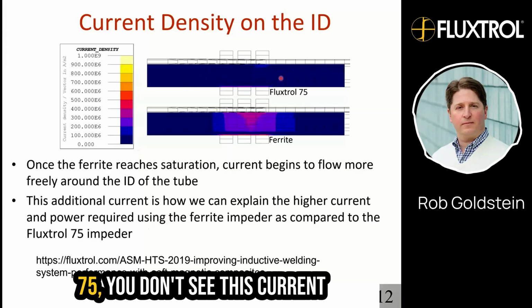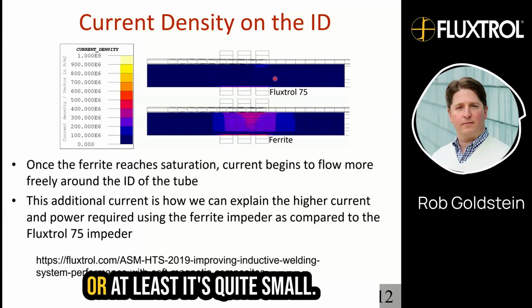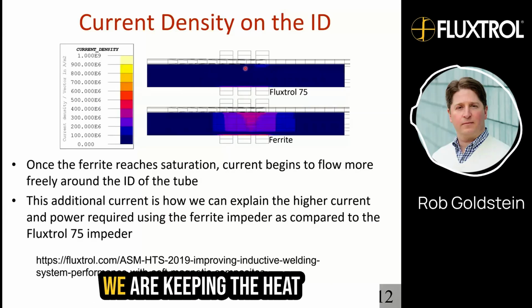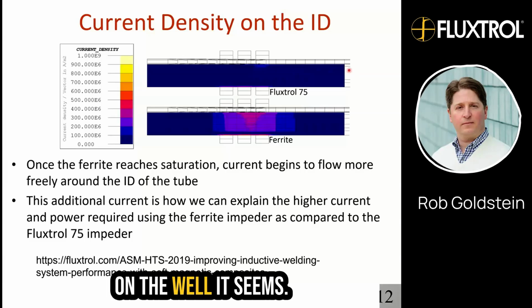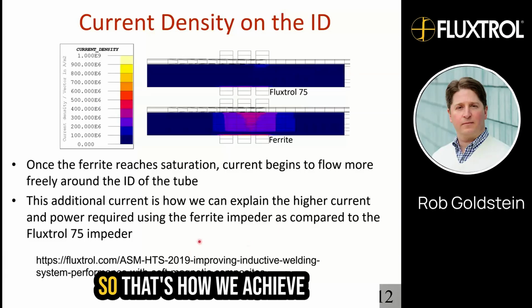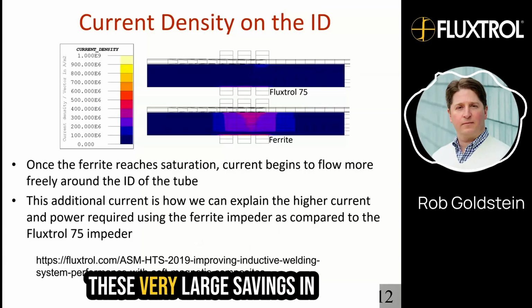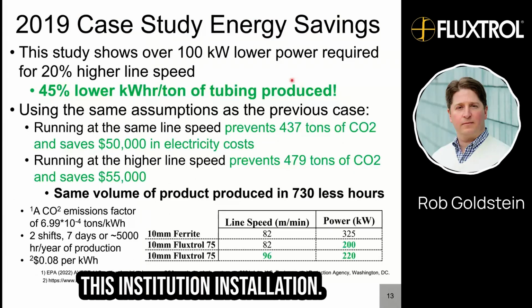Meanwhile, with the Fluxtrol 75, you don't see this current, or at least it's quite small. We're keeping the heat on the weld seams. So that's how we achieve these very large savings in this installation.